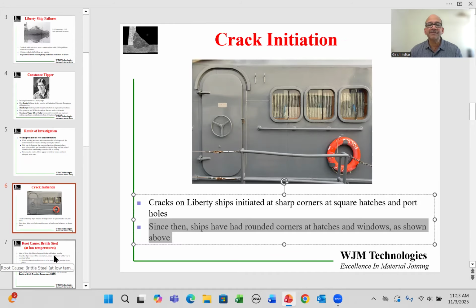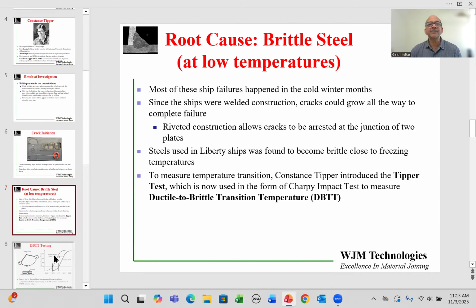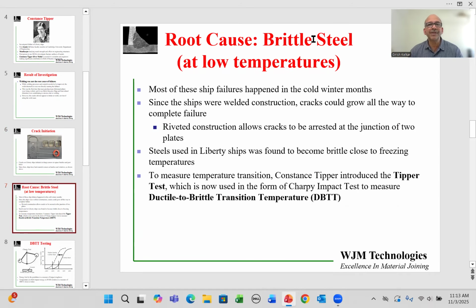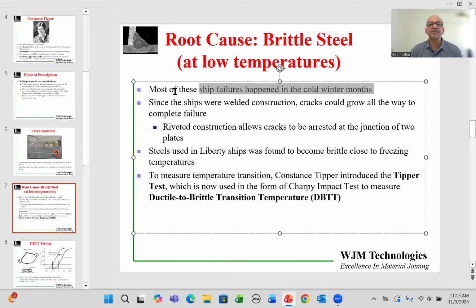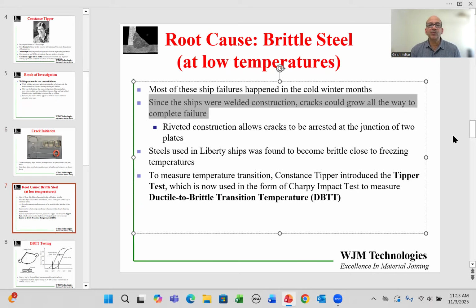However, the cracks themselves did not cause such a massive disaster. The root cause was the brittle steel at low temperatures. Her investigation revealed that most of these ships failed in the cold winter months. Some were actually failing right in the harbor itself. Since the ships were of welded construction, cracks could grow all the way to complete failure.